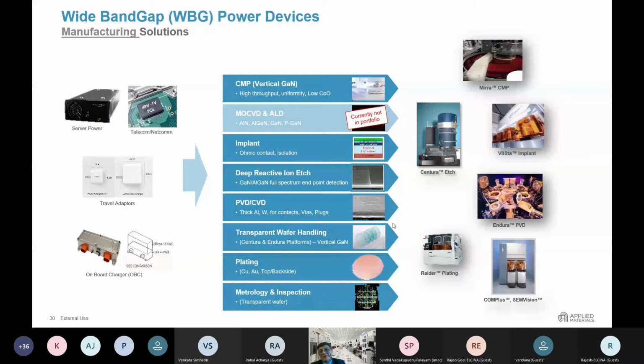of measure. And it was only in the last few years that this defect density has been controlled a lot better, so that this technology is now being seen as a potential mainstream technology. Even then, there are constraints. So you don't actually make these wafers on a 12-inch wafer. You don't make it on a 300 mm wafer. You find that because of the warpage that can happen because of the crystal mismatch and the production constraints, people are actually making gallium nitride and silicon carbide on wafer coupons of sizes 4-inch and 6-inch, and maybe even 8-inch. But nobody is really looking at a large scale 12-inch production.